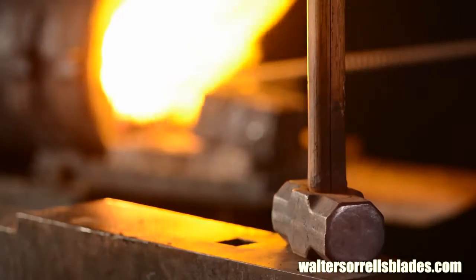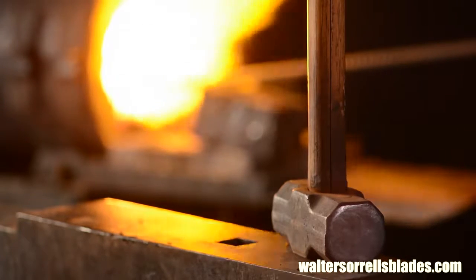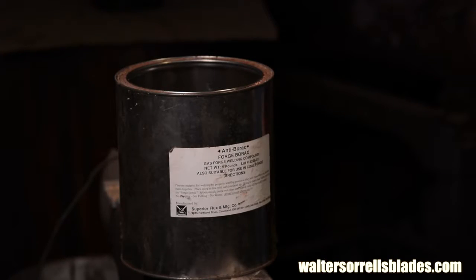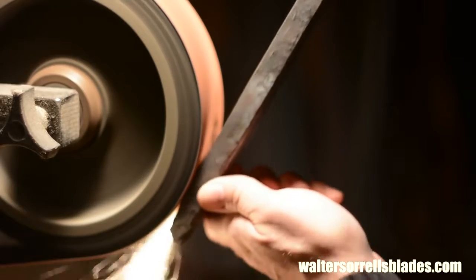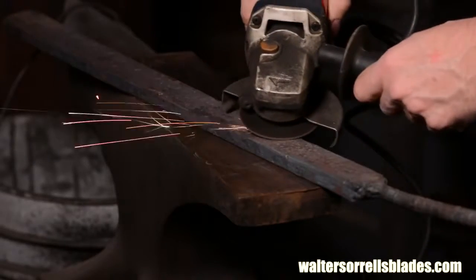One thing to note, if you're using a nickel alloy, nickel oxides are very hard to get rid of, and borax flux won't necessarily do the trick. You may need to pull the billet out and hit the face of the billet with the grinder. Some people like doing it with an angle grinder. That's a good method too.